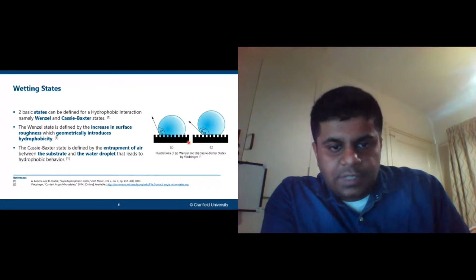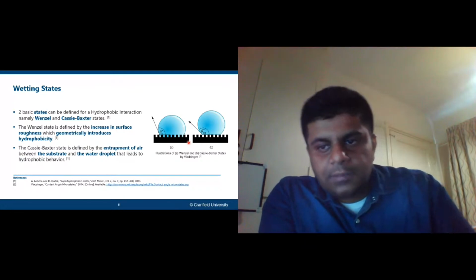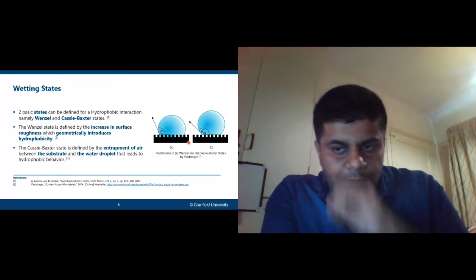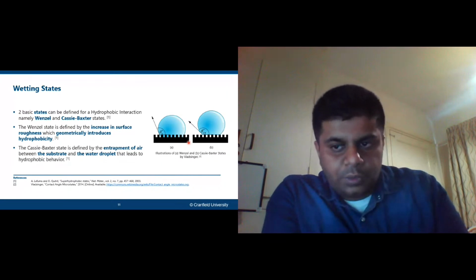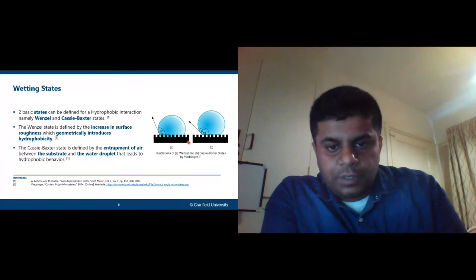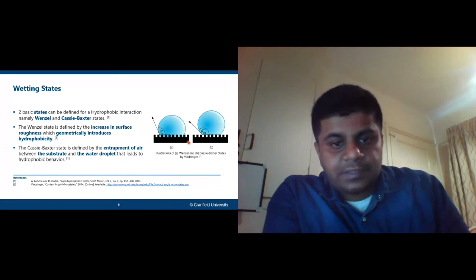In the next, which is the Cassie-Baxter model, the droplet is not in intimate contact with the bottom of the surface, but only on the top, and the rest of the bottom is filled with a fluid, or air in this particular case. So you actually receive very small tilt angles. A tilt angle is when you move the surface to a certain angle, say less than 5 or 10 degrees, and the droplet just slips off. So that is when you have the Cassie-Baxter state.